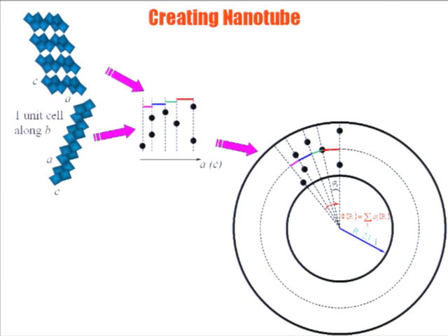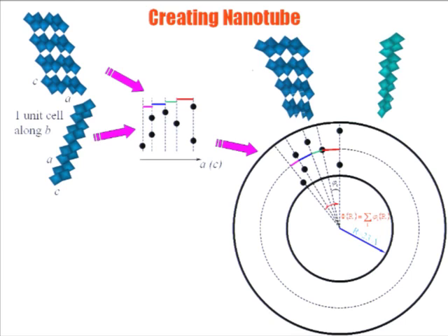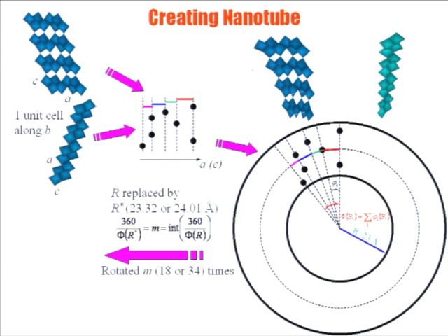This is to emphasize that in the middle of the tube, the distances are exactly as in the bulk structure. By doing this, those two fragments start looking like this, and then we can take these fragments and fill up the whole tube. While doing this, we needed to readjust slightly the radius in order to get a seamless junction, but it was just a matter of solving this transcendental equation, not a big deal.